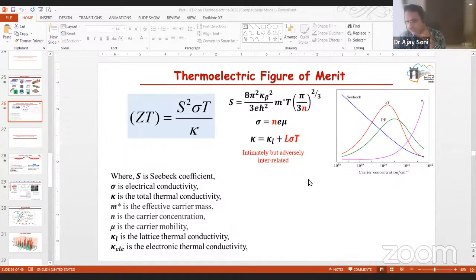So what happens is, when you talk about the number of charge carriers, the limitations come from the Wiedemann-Franz law, because it will increase the electronic part of the thermal conductivity, and that will increase your denominator. That's one of the biggest hurdles. Second, the Seebeck coefficient is inversely proportional to the number of charge carriers, so if you have more charge carriers, the Seebeck coefficient is low. But even with a high number of charge carriers, which is the case in SnTe, what we are targeting is to increase the effective mass. So even if the number of charge carriers is large, you ask them to walk slow, which means the mobility is poor.